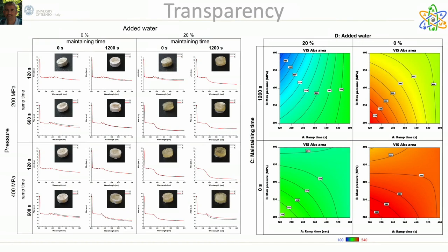Analyzing the absorbance values against addition of water and maintaining time, it resulted clear that the dry material was incapable of granting low absorbance levels. Among the samples exposed to water instead, those showing higher transparency were the ones maintained under pressure for longer time. Given these conditions, the shortest ramp time, 120 seconds, and highest pressure applied, 400 MPa, resulted in the most transparent samples, in which all the fibroin flakes were sintered in a continuous thermoplastic material.